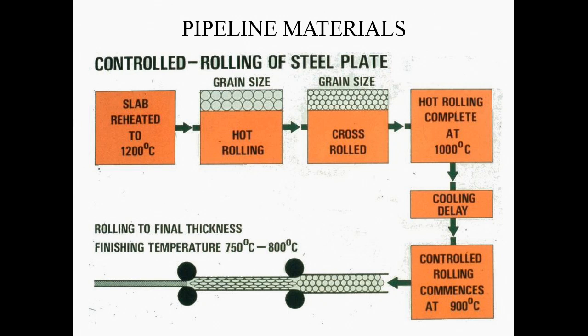So it went into the rolling mill at 1200 degrees C. We haven't controlled the temperature by reheating all the time, but by the time that process is finished, we've gone down to about 1000 degrees C. So that fixes the time that you have. Normally this thing is rolled, rotated and rolled back, and that process will take a couple of minutes, something like that, which gives you this temperature drop. Then there is a cooling delay because the controlled rolling process we don't start until we get to 900.